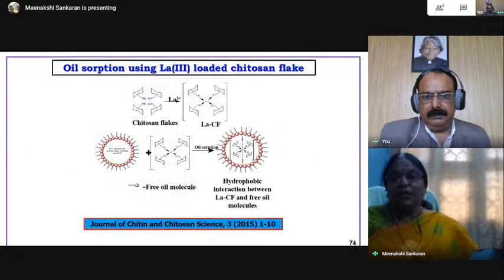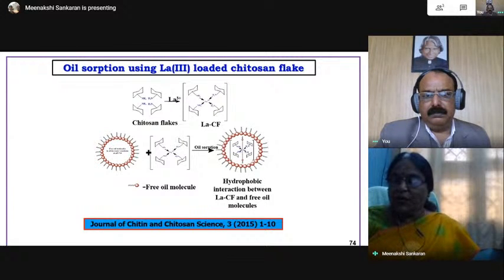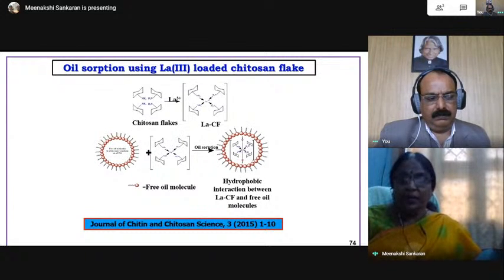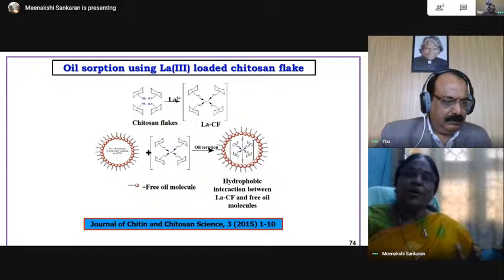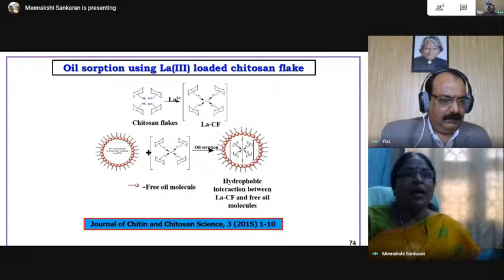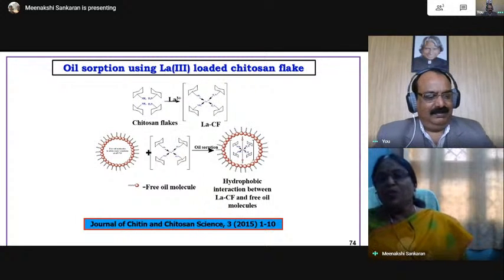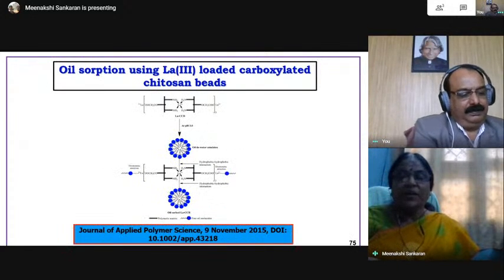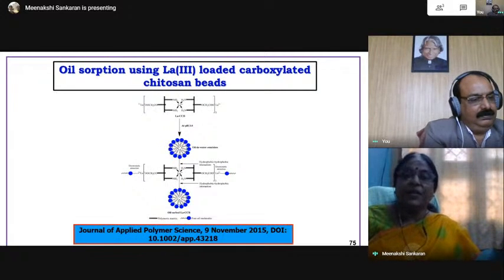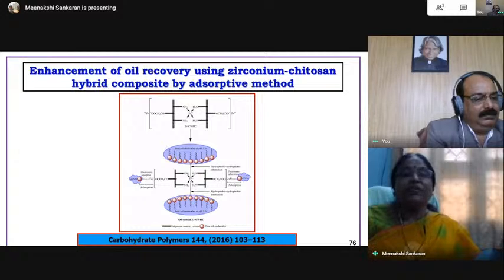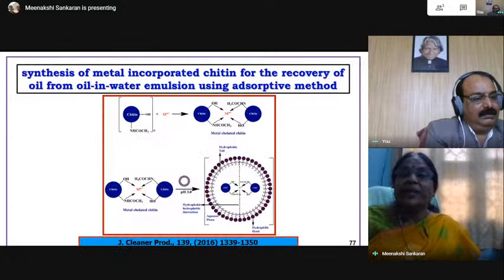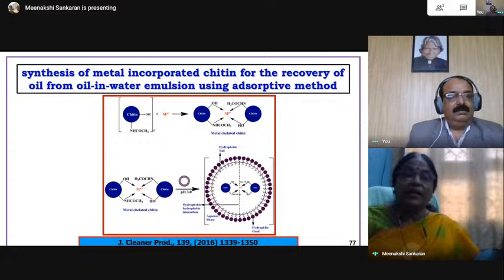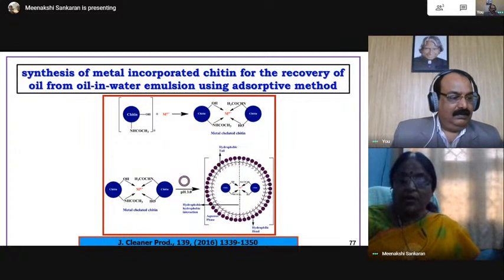For that, oil is hydrophobic. Therefore, we have made our material hydrophobic, and we have used chitin and chitosan for the recovery of oil. Oil formed a stable emulsion with water. The first step is to separate oil and water, and then we have to remove oil from water. These are the various materials we have prepared: lanthanum loaded carboxylate chitosan beads and others for the recovery of oil from water. We made hybrid composites, and this is metal incorporated chitin. Chitin is more hydrophobic than chitosan, so this showed a higher capacity for oil removal.